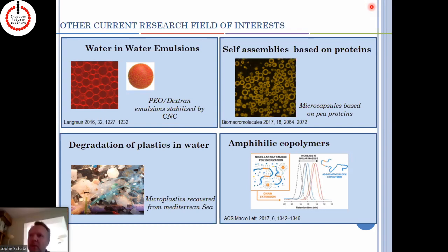Okay, so ions are not an issue. No, because remember we have acrylic acid, so as long as the amount of divalent cation is low, it works perfectly. But if you have too much calcium, for instance, you will have the tendency to have some precipitation due to the complexation by acrylic acid.